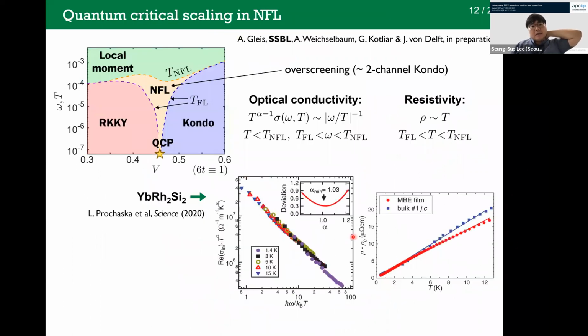And we also studied the nature of this quantum critical regime. We found that it is governed by this overscreening behavior. Again, we are using a DMFT type method, so it is now a matter of the Kondo effect. And this overscreening is similar to what's happening in the two-channel Kondo physics. And based on that, we computed numerically and also had an analytic explanation of this quantum scaling behavior of the optical conductivity and resistivity. So there is no characteristic energy scale coming in, so they are quantum scaling.